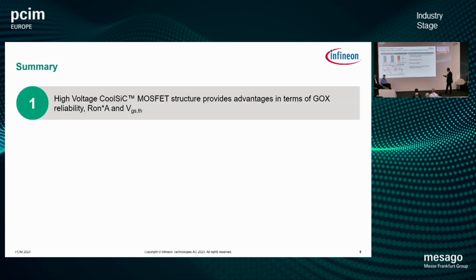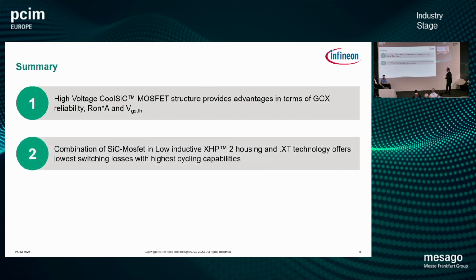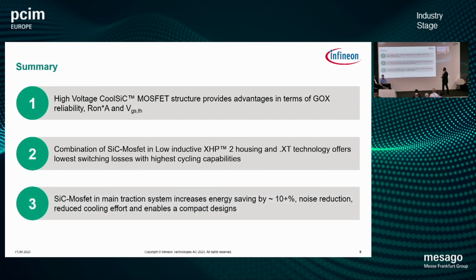With this, I'm at the end of my presentation, where we would like to summarize that the high voltage silicon carbide MOSFET structure gives us an advantage in terms of the gate oxide reliability, the RDS(on) times A, and the threshold voltage. The second aspect is that the combination of silicon carbide in the low inductive XHP housing and .XT technology makes a good combination of silicon carbide with lower losses and a higher cycling capability. And what it brings at the end is that for the traction application, the energy saving is in the range of around 10%. There is another benefit in terms of noise reduction, cooling effort, and it enables a compact design.